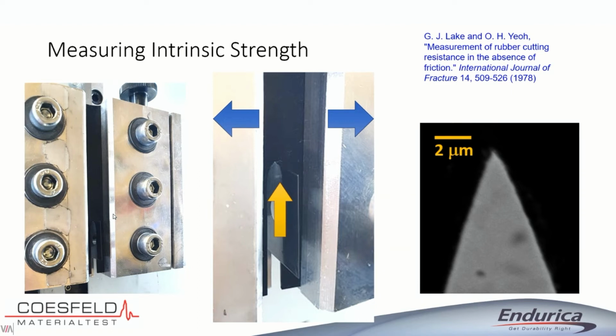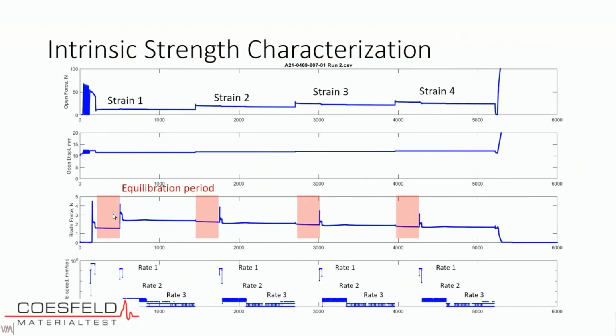The blade is instrumented so that we can measure the forces that act on the blade. We use a blade that's as sharp as you can possibly get. It's a blade from a microtome, so it's nanoscopic sharpness. And the idea in the experiment is to drive the blade through the rubber at a series of different rates. There's a matrix of things that we do, but when we push the blade through the rubber, we do that with the rubber stretched and strained a little bit. And typically we'll do this under a series of strain levels, maybe 4 strain levels.